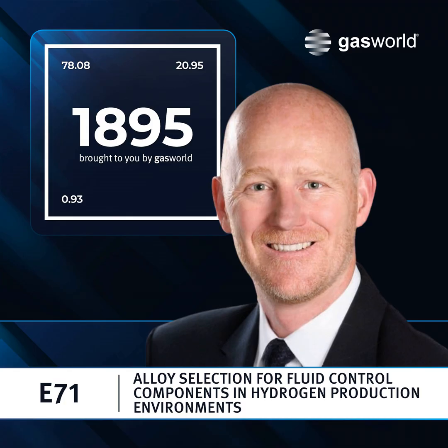After the initial SMR reaction, there's a water gas shift reaction that converts the carbon monoxide and water in the stream to more hydrogen. That process occurs at lower temperatures, around 180 to 250 C, and employs a catalyst and reacts the carbon monoxide and water. Pressures are a little bit higher than in the SMR reaction, on the order of 10 to 60 bar. But again, high quality 316 components are effective, cost-effective solutions there.